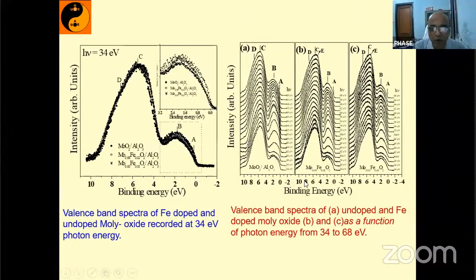So this type of problem also one can do, because here you can see that only 2% or 5% doping is there. In normal laboratory level photoelectron spectroscopy, you will not get the signal from the iron itself. If the iron signal is not there, then you will not get any information about what the doping is doing. But because in synchrotron radiation photoelectron spectroscopy the intensity is very high, one can get good quality spectra. And one can do good quality analysis using these spectra and find out what is happening once you dope iron into the molybdenum oxide.